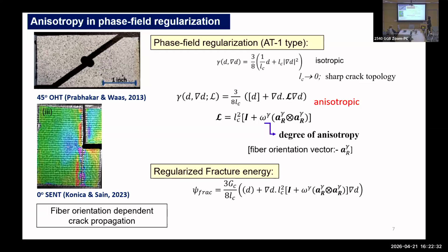So what we did is, this was the typical crack density functional incorporating a homogeneous damage field and a gradient of the damage field. That gives an isotropic crack growth very nicely, and it's very well known in the literature, like the early studies of phase field crack growth. To begin with, we introduced an anisotropic tensor in the gradient term. If you look closely, the anisotropic gradient term has a scalar variable omega and this dyad, the tensor, which essentially represents the fiber planes.